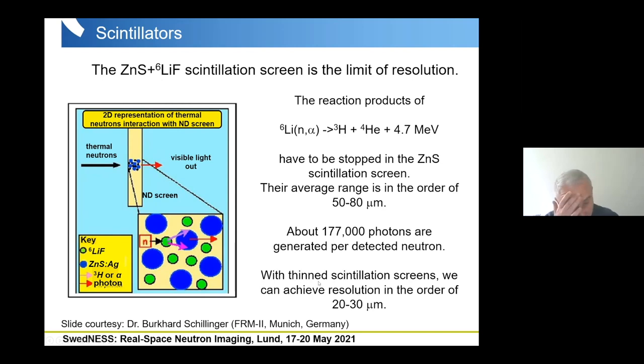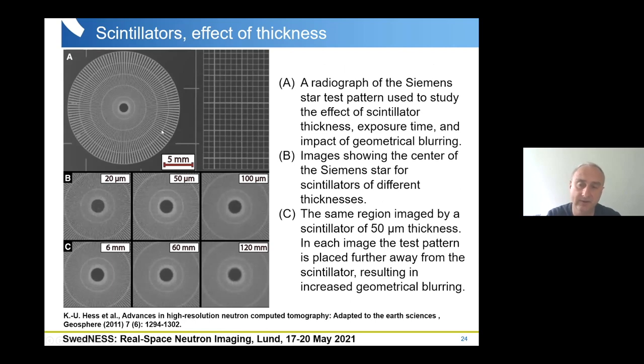What I mean with thin scintillators? So you can see here the effect of the scintillator thickness on the resolution just by imaging of this Siemens star. And here you see actually the performance of the detector system for different thickness of scintillators. And it is obvious that at thicker scintillators, we lose resolution. So also the effect of the geometrical blurring is shown here. So here for the second row, we use the same scintillator thickness, but different distance between the Siemens star and the detector. So at very short distances, we see that we have the best resolution, and increasing the distance between the Siemens star and the scintillating screen, the resolution is quite worse.